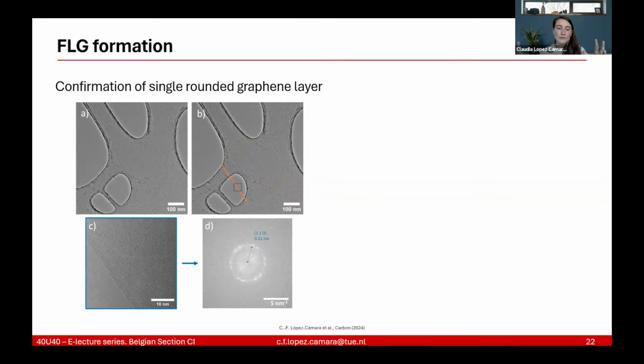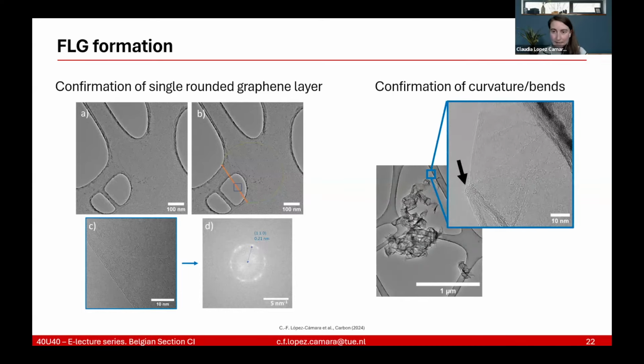The other question we had was, when the graphene self-folds, does it break bonds or form new bonds that other species or components can attach to, or does it just bend and form a curvature? We confirmed that it was forming a curvature, or bending, by this picture, for example. This is a very crumpled graphene, and you can see a zoom in of that part. In the zoom in, you can clearly see at the pointed arrow that it makes a curvature rather than a break. Therefore, it does not leave bonds open, but it just self-folds, creating a curvature, which means that at that part there is no possibility of growth anymore, because there are no new bonds created. And that's something that we also wanted to see in this picture.